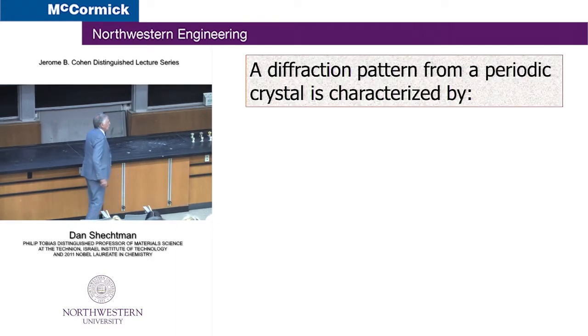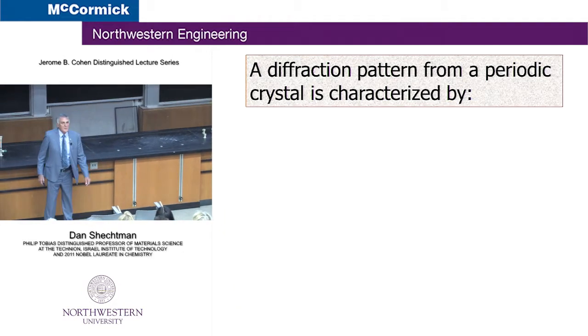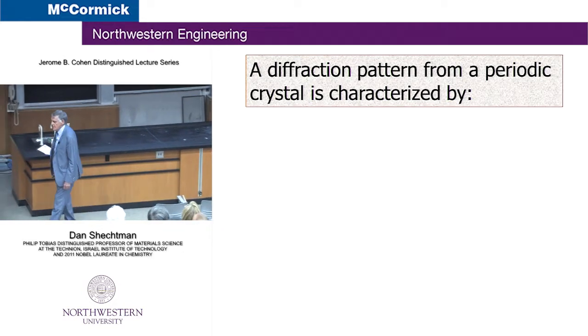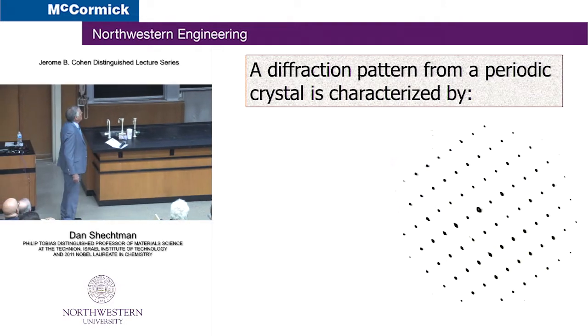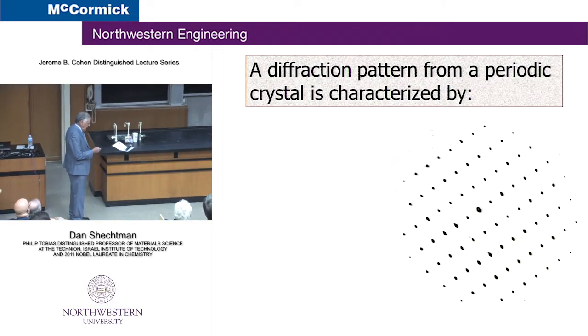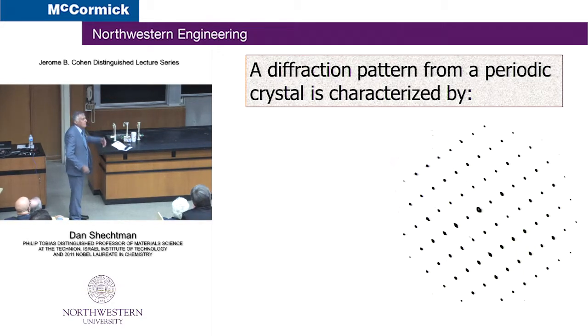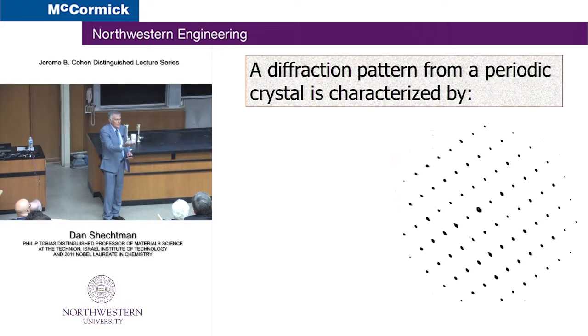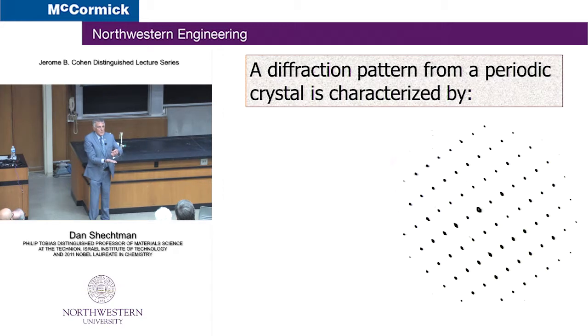Now, let me take you to the reciprocal space. This is a space in which the diffraction patterns exist. And this is, by the way, an electron diffraction pattern taken from a periodic crystal. And the diffraction pattern is also periodic. If the crystal is periodic, so is the diffraction pattern. So what you see here is this fat spot in the center is the transmitted beam, and all the other spots are diffracted beams. What you do in an electron microscope, you shine an accelerated beam of electrons onto a specimen, and the specimen is very thin.